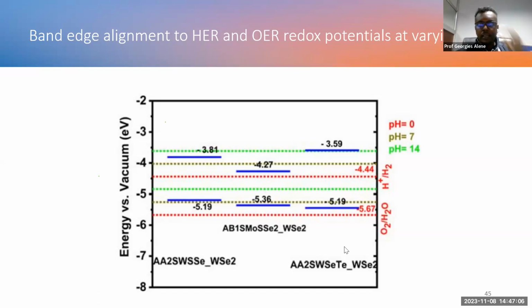And one interesting thing is, for this WSSe-WSe2 system, when you see the pH at 7, the band edges are lower than the redox potential and higher than the redox potential of water. And this is actually very good for water splitting. And this system, at pH 7, is suitable for overall water splitting. It can do both the oxygen evolution reaction and the hydrogen evolution reaction.